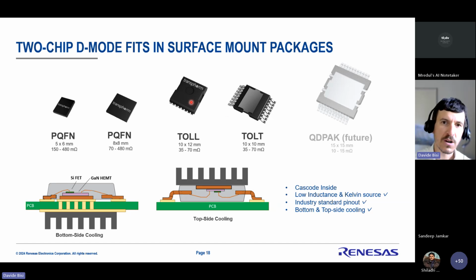As you can see here, we offer them both in a bottom side cooling, where the heat sink is at the bottom of the package. So you can see here the cross section with the silicon FET, the GaN HEMT, the lead frame of the package, and then the circuit engineer has to make thermal vias through the PCB to extract heat through the board, and you can see the heat sink on the other side of the PCB.